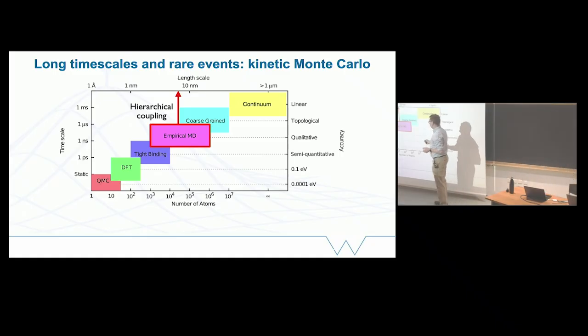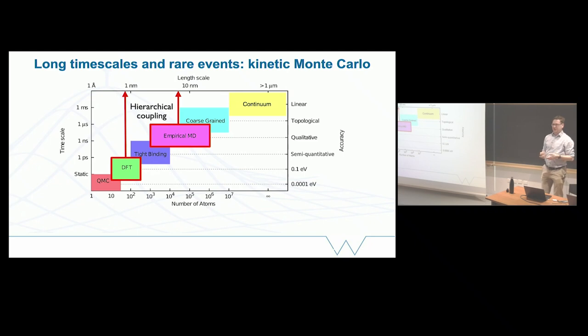Okay, this is where I was going to mention coupling up to larger timescales. So once you've done this kind of thing, if you can extract energy barriers, so rates of processes, then you can parameterize a kinetic Monte Carlo model. You could do it using a potential, or if you're concerned about the accuracy of the potential, you might be able to do it directly with DFT, although these calculations that you have to do in order to compute barriers, these nudged elastic band calculations, are quite expensive and quite hard to do. So maybe this is something to keep in mind for the second part of the talk, that we'd like to be able to compute these kind of things without directly doing the DFT calculations.